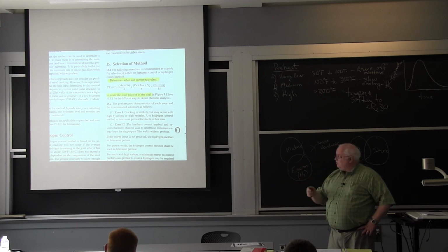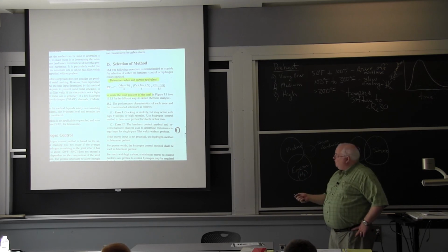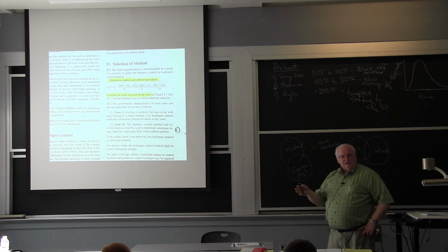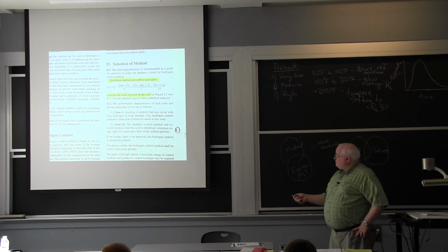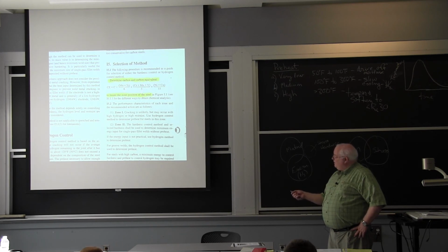One was a function of the carbon content, the other is a function of the thickness and of the alloy content. Well, the carbon equivalent is basically a measure of how deep I can harden that heat affected zone in that steel with a certain alloy content. So it starts with the carbon, and manganese and silicon don't add as much hardenability as carbon does. You divide by 6. Chrome, moly, and vanadium, you divide by 5. Nickel and copper, you divide by 15.